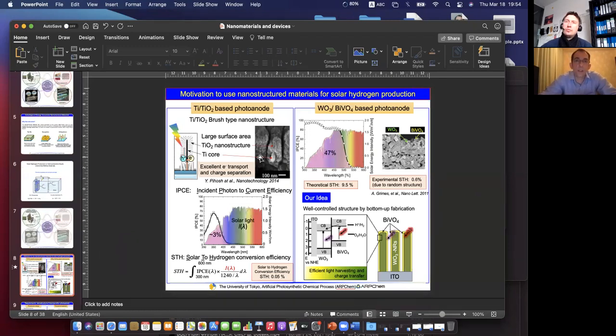Yeah, Roman. Actually, this is what we did in the next work. So this is the similar case. So actually bismuth vanadate is a shell structure, okay, and the core is tungsten oxide. That's shown here. This is the design, okay. However, this technique is completely different. So this is anodization technique. But here is the combination of two different materials, so for that reason, we need electrochemical deposition.